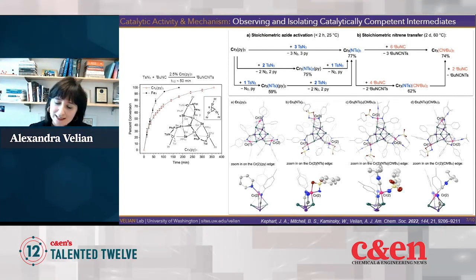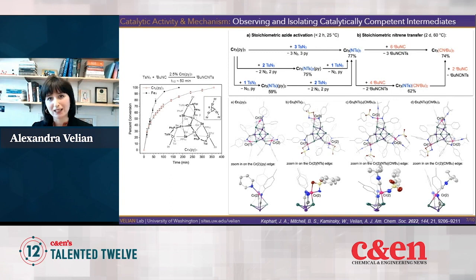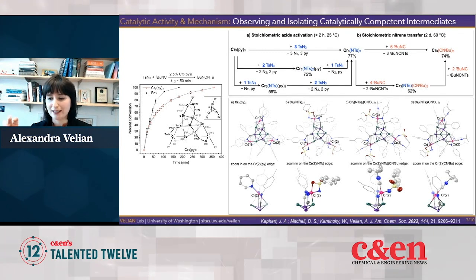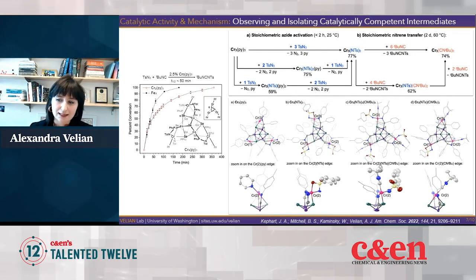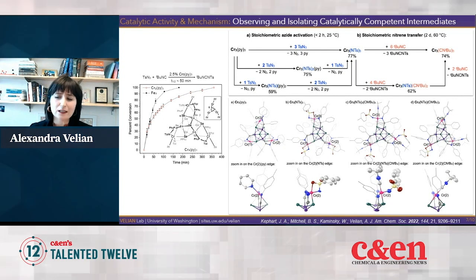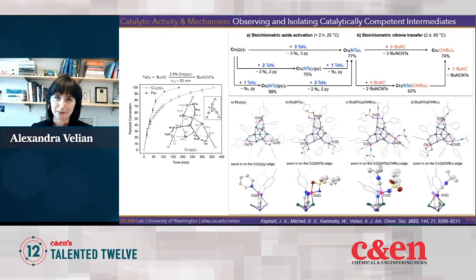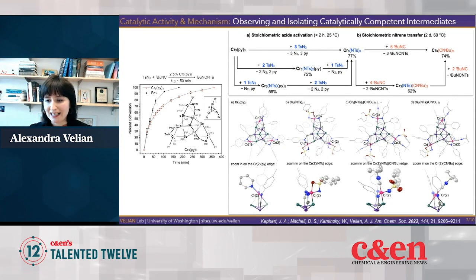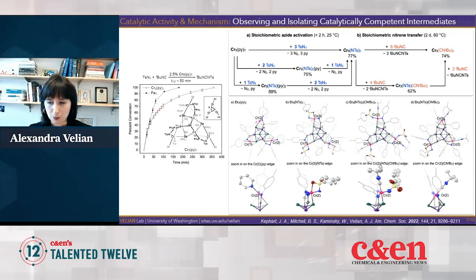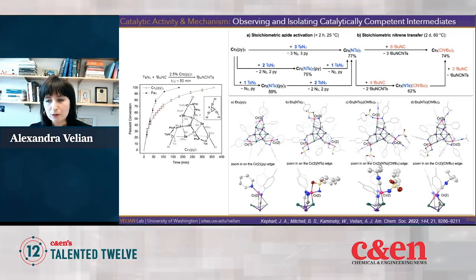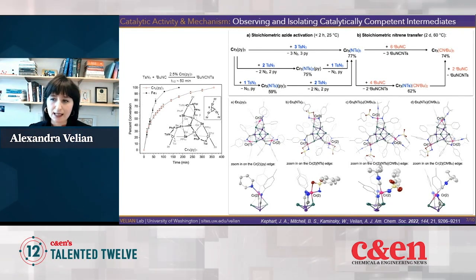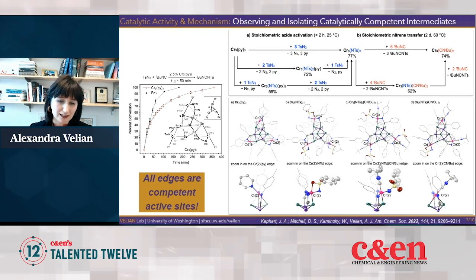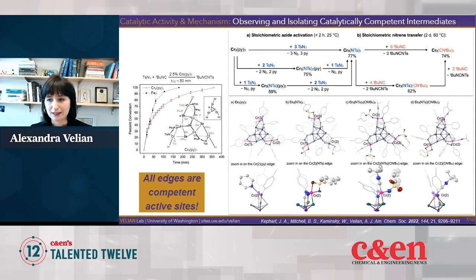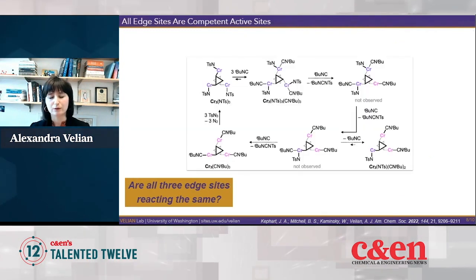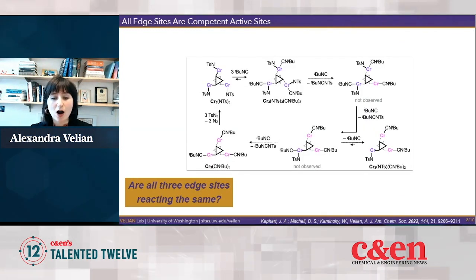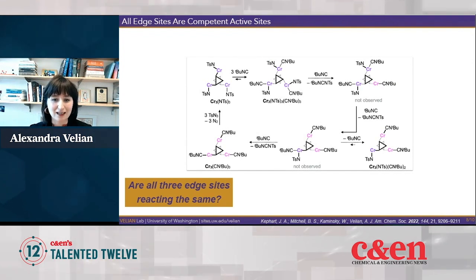It's kind of cool. This edge site doesn't directly spit out the product, even if both substrates are bound to it. But then we think a second equivalent of the isocyanide comes in to finally release this chromium 2 site bound to an L-type ligand. And of course, the final product. Although it was really great to see directly that all of the edge sites are in fact catalytically competent active sites, the question that really is on our mind is, are all of these edge sites acting the same way?